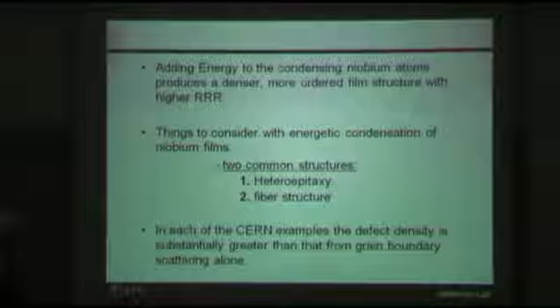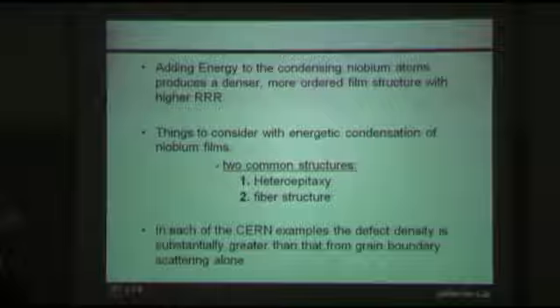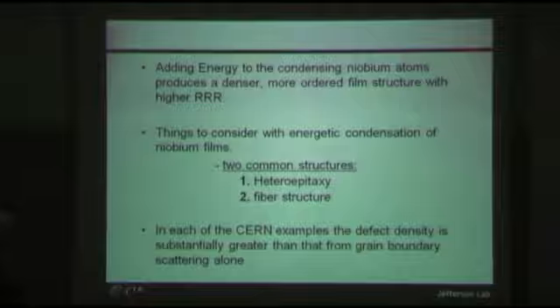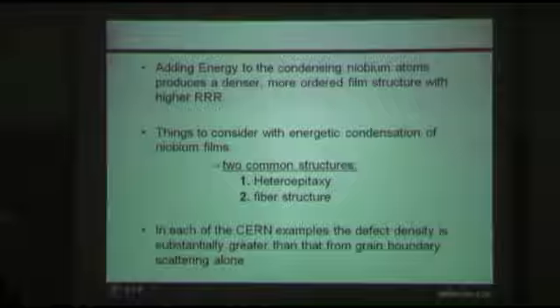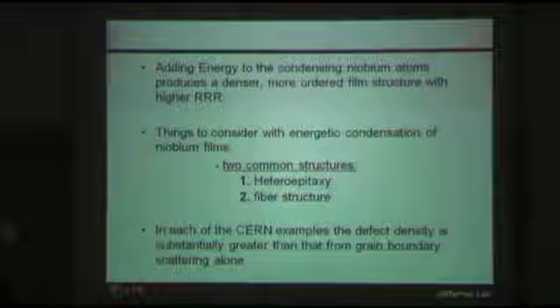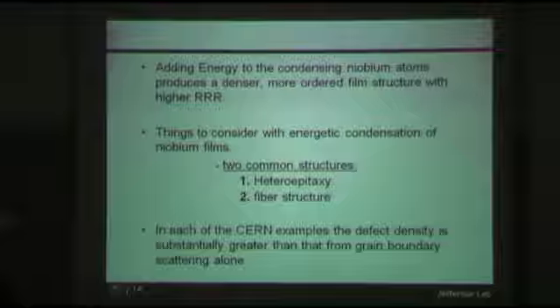After nucleation at the substrate surface, grain competition, in the case of fiber growth, will occur during grain growth, with the grain having the lowest surface energy predominating. And in the case of niobium, that would be the 110 plane surface. A potential advantage of this is that it will avoid surface roughening due to preferential sputtering by the incoming ion beam according to the differing surface energies of each.